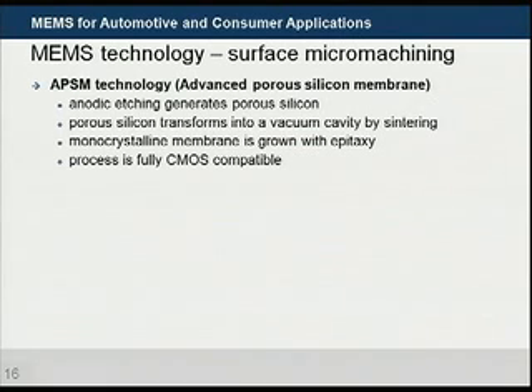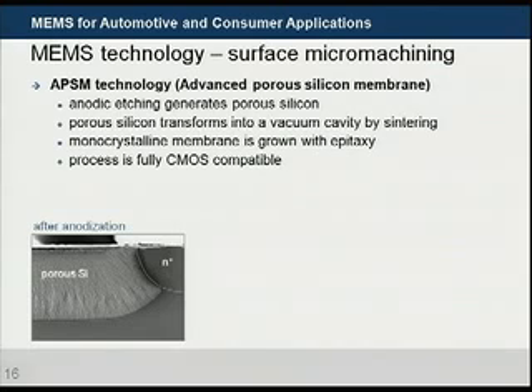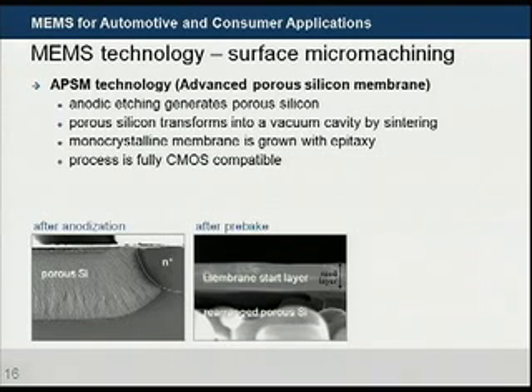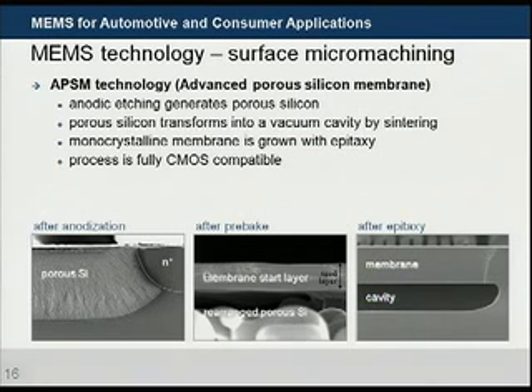Another example of the surface micromachining is the advanced porous silicon membrane technology. For this technology, we are using anodic etching to generate porous silicon. The density of this material is very small, and therefore, as we go into a sintering process, this material will collapse. We have a membrane, which is a seeding layer for epitaxy, and with the epitaxy, we can grow a very good monocrystalline membrane with excellent semiconductor properties on top. And as you see, by the porous silicon, which was on the bottom, we've been able to create a cavity with a vacuum below this single crystal silicon membrane.